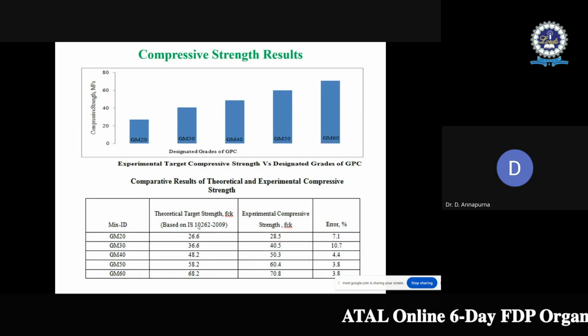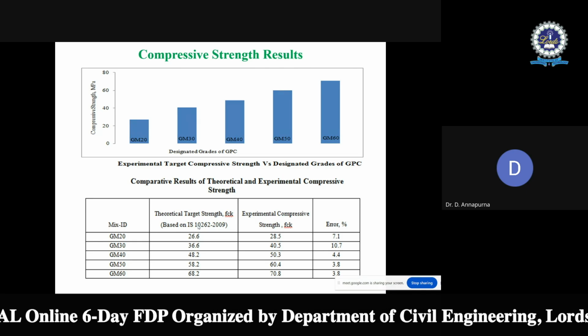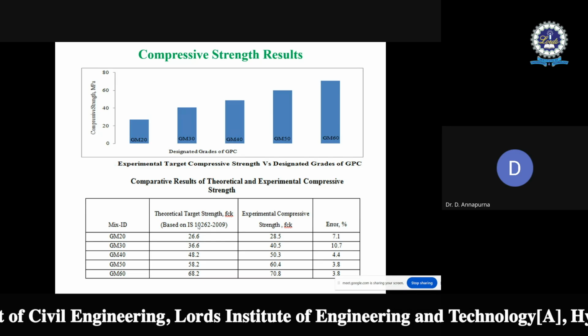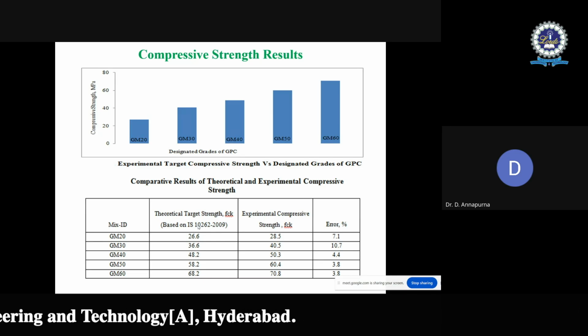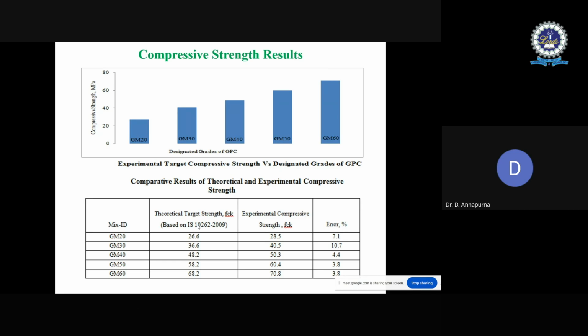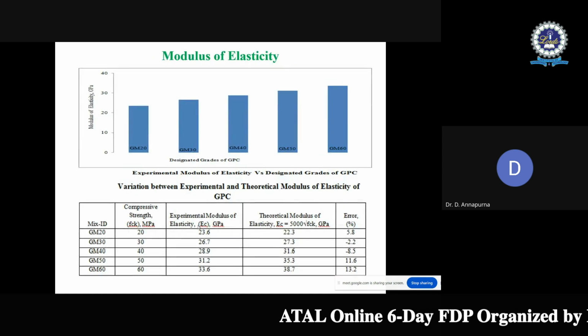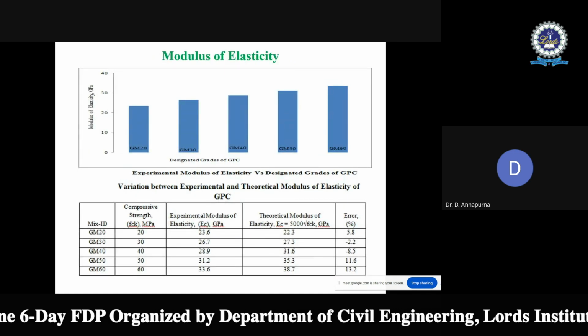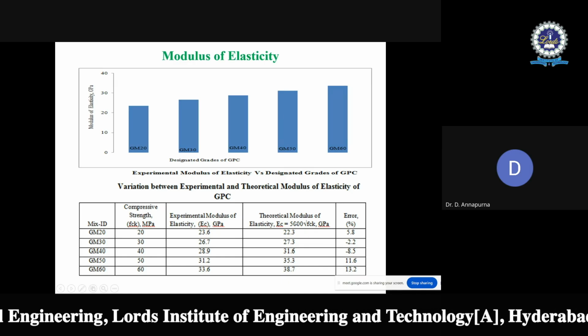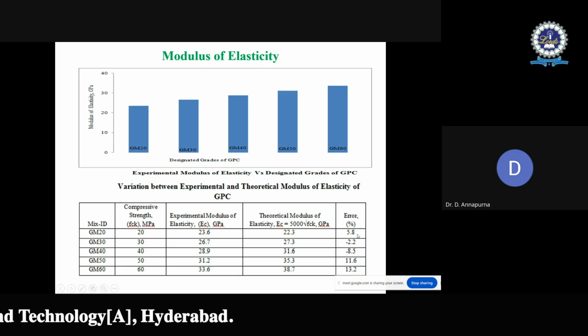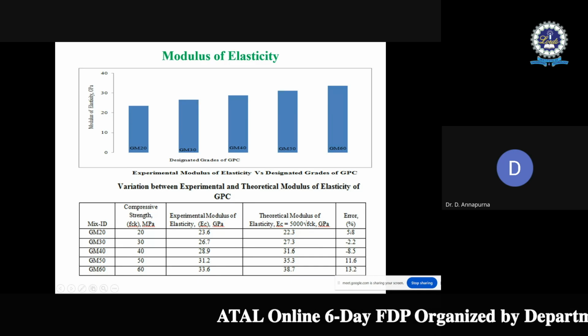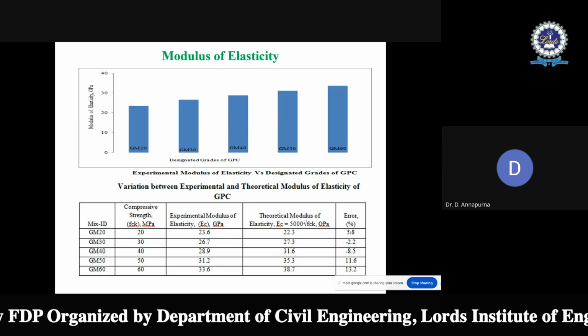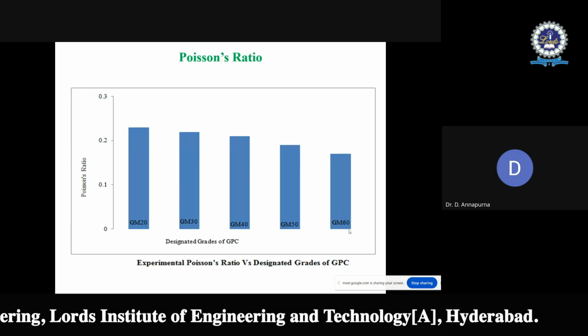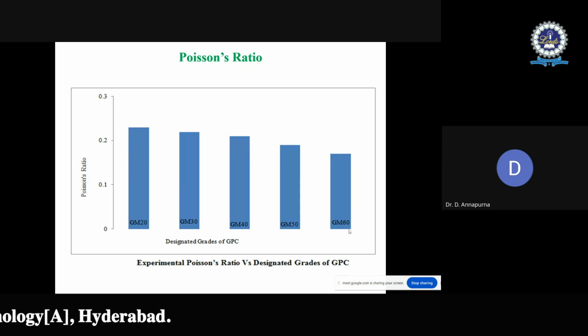Then in the second stage, all the mechanical properties are identified, like compressive strength, flexural strength, and tensile strength. All the mechanical properties of this geopolymer concrete are meeting the level of normal conventional concrete of the same grade, M20 to M60. This includes the modulus of elasticity: the theoretical modulus of elasticity, calculated as per Indian Standard IS 456, is compared with the experimental modulus, and the percentage error is within 15%. So it is giving a good comparison. It is meeting the level of conventional concrete. All the proposed grades of geopolymer concretes show the same level of mechanical properties as the conventional grade. This is about the mechanical properties.